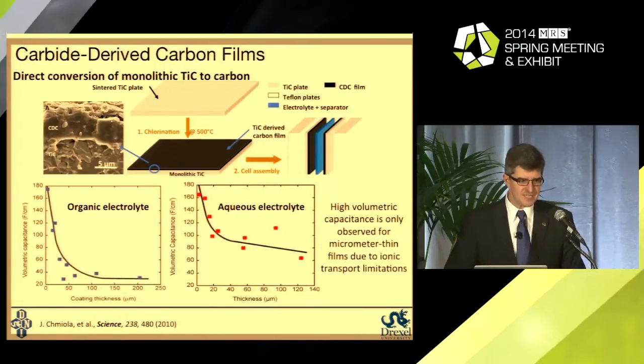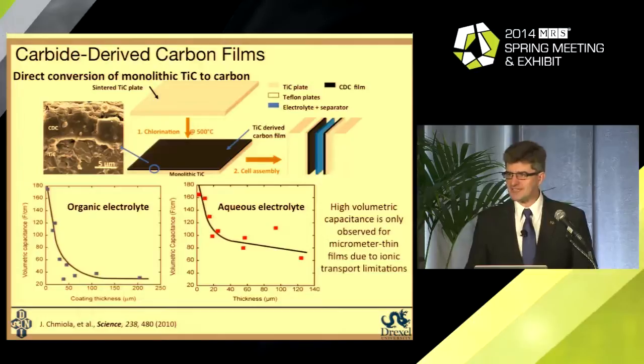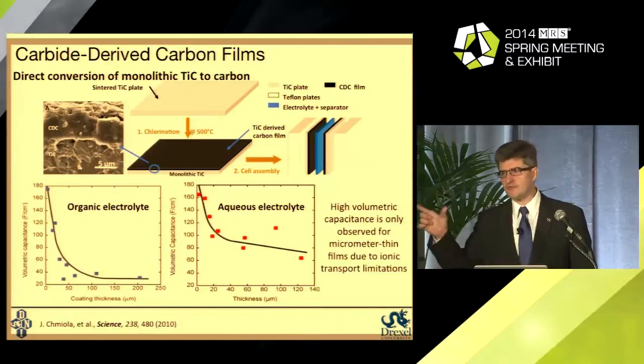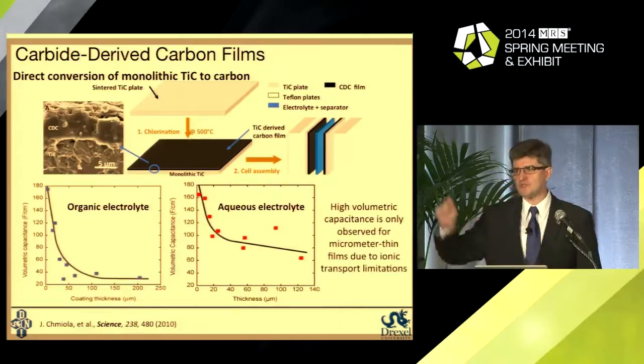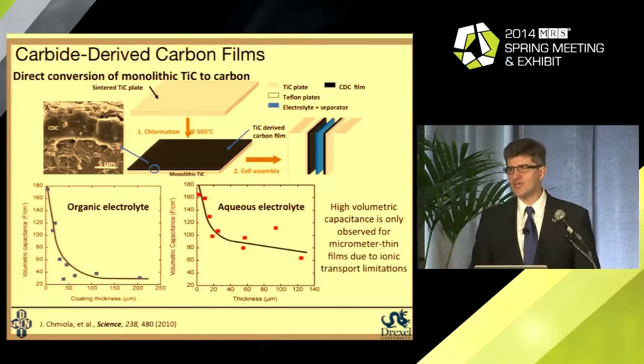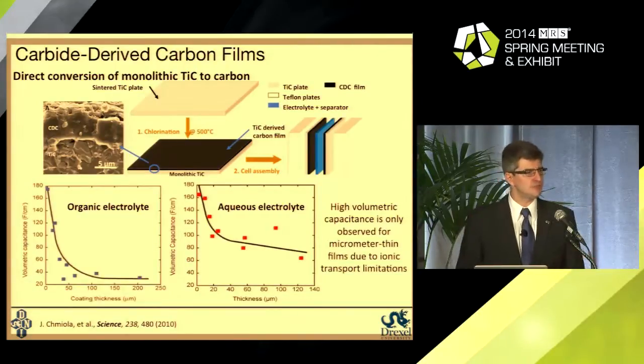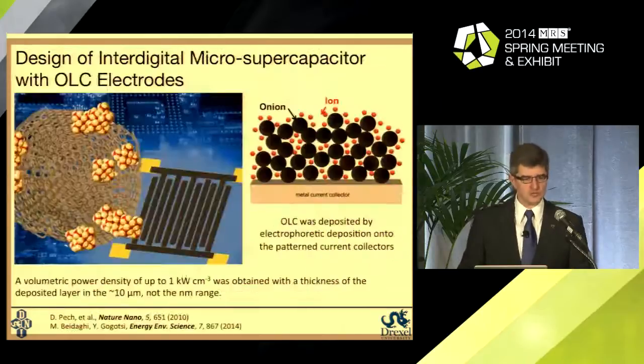But as you see, just for 1 micron films. As the film thickness increases, capacitance decreases, going actually below state-of-the-art devices. And the reason you can understand in a very simple way. Consider you have a 100 micron thick film with 1 nanometer pores. An ion must jump through 100,000 pores to reach the current collector. Of course, we simply hit diffusion limitations. We cannot fill all the pores. We cannot store charge efficiently here.